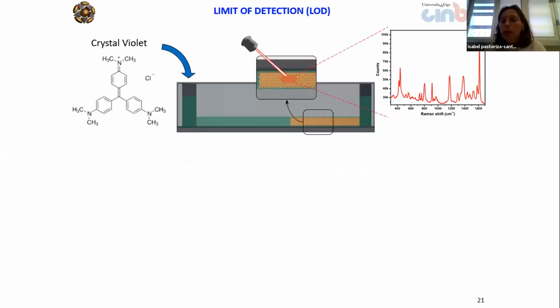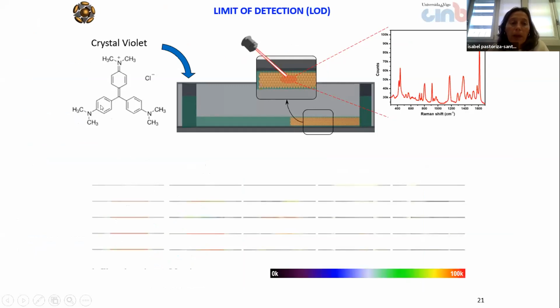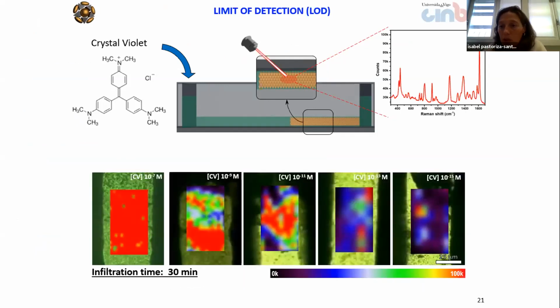So next, in order to test if our plasmonic microchip would be interesting for sensing, we tested the limit of detection. In that case, we use crystal violet, which is a pollutant, and we infiltrate and test with different concentrations of the molecule. And in principle, as you can see here in these SERS intensity maps, we are able to detect, after using an infiltration time of 30 minutes, down to 10 to the minus 15 molar. Also, as is obvious, at large concentration there is a uniform distribution of the molecule in the whole supercrystal, and when the number of molecules decreases, we observe that this uniformity is lower.